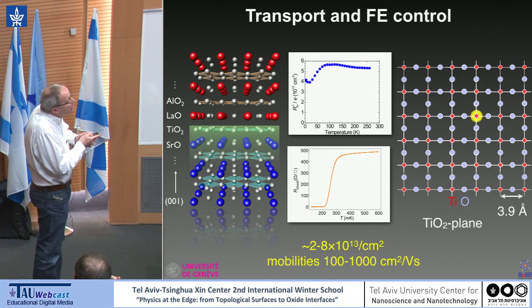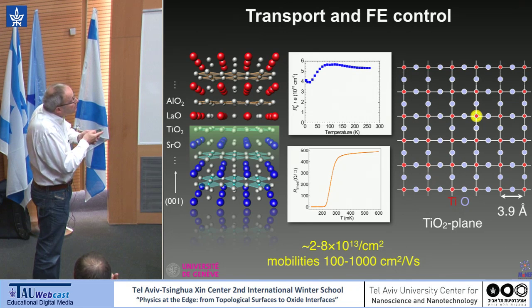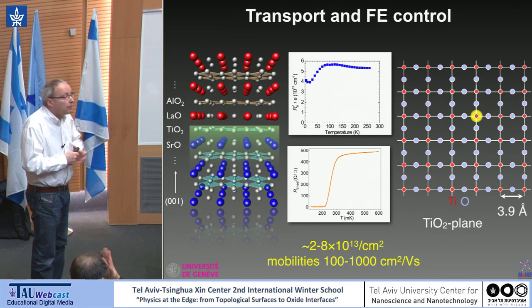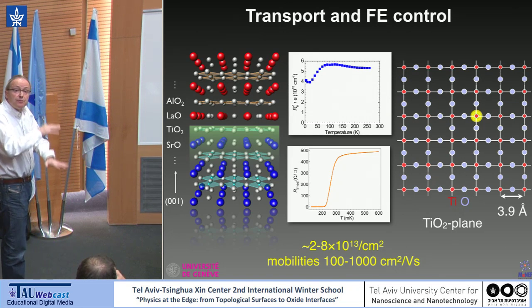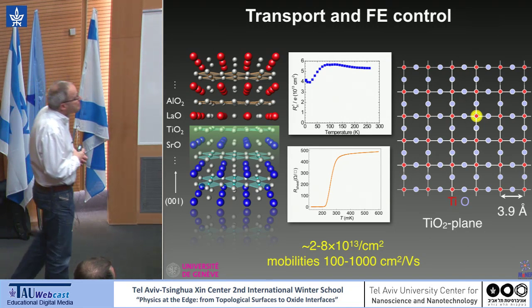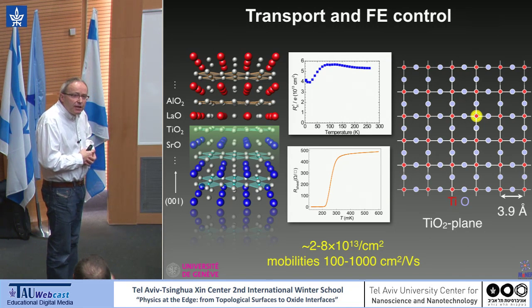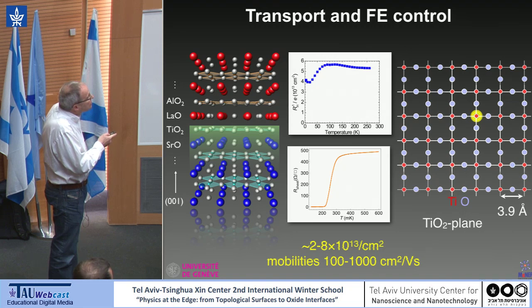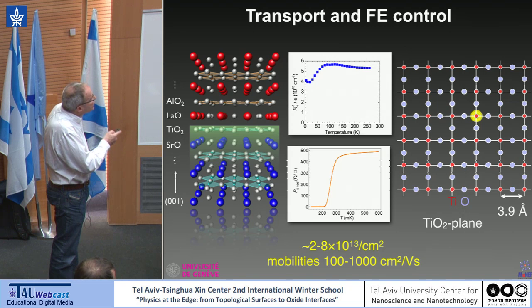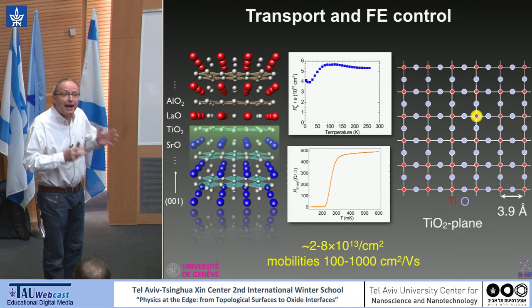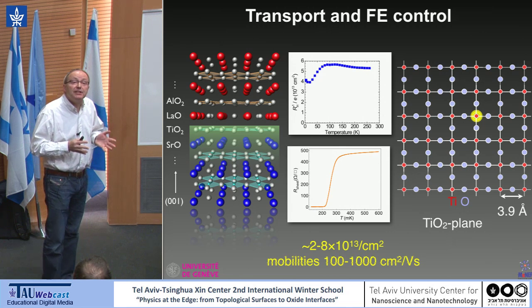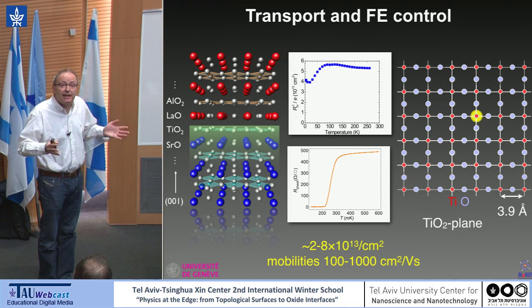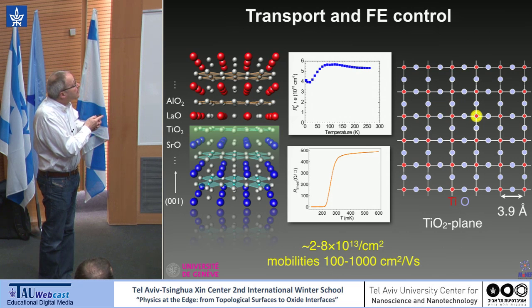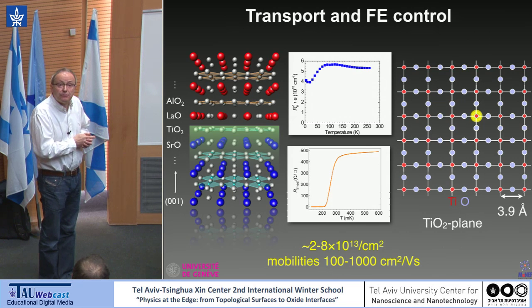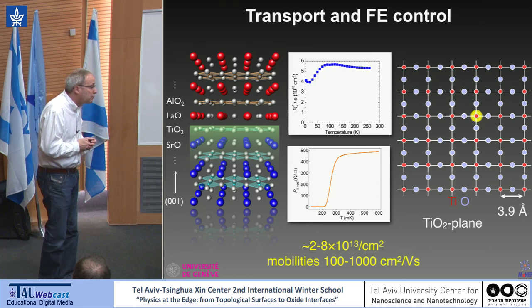If you think about it, it's 1 electron every 25 unit cells looking from the top, and these electrons are spreading over several nanometers. Now, if you look at our structure with our electron liquid, which is here, between two insulators, this is an ideal situation to perform a field effect experiment, because your gate dielectric is already there. You can either use lanthanum aluminate or you can use strontium titanate.